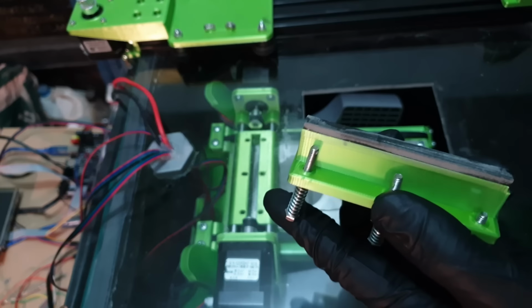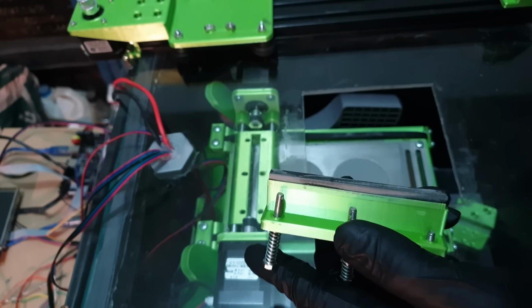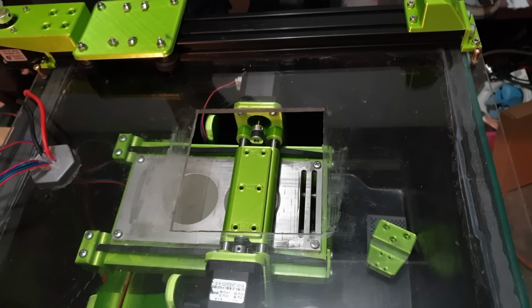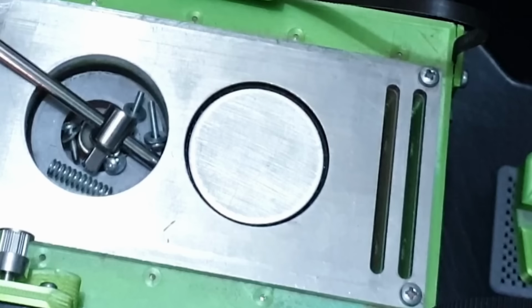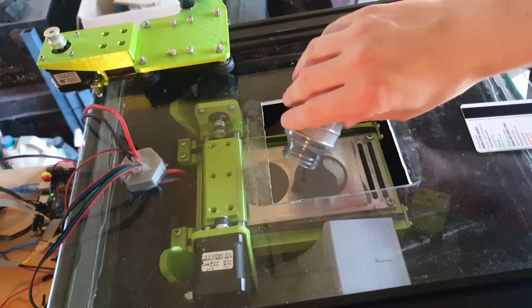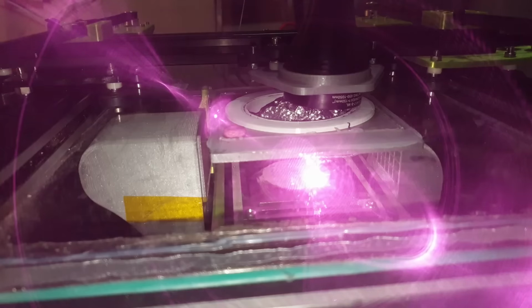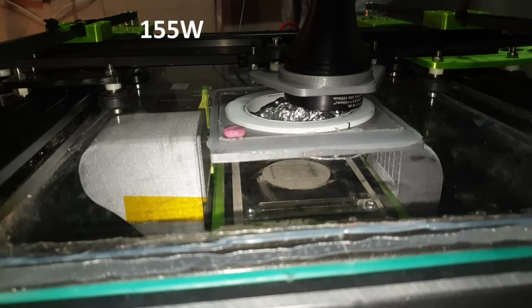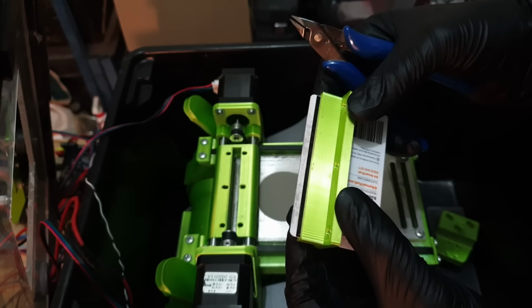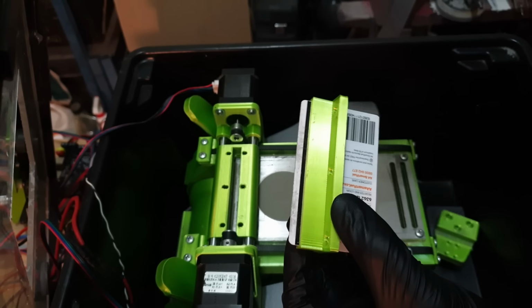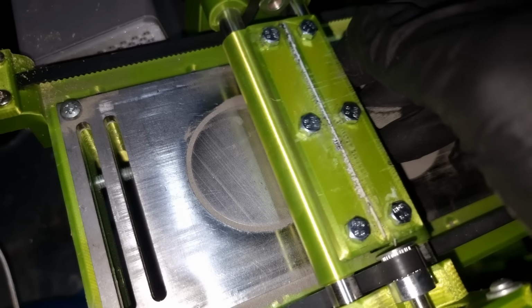And as to why, if memory serves me correctly, I'd had a lot of trouble trying to get the powder to cleave effectively, even going to the length of sanding the substrate to stop the powder from sliding over it. Eventually I just accepted that the first layer would be higher than the following layers, turning the laser up to 11 and calling it done. But unwittingly, I'd already solved this issue with the use of a plastic swipe card, but not until I found myself constrained for power would I have to reconsider this.